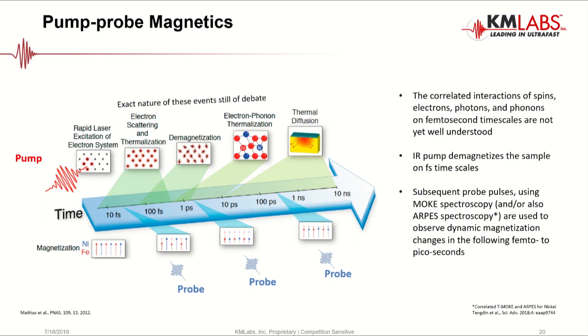One more example of the pump probe is to look at magnetics or spin behavior in materials. And it turns out for magnetic materials like iron or nickel or cobalt, when you hit them with a pump laser of the right wavelength and energy, an interesting series of events can unfold on the femto to pico and nanosecond time scale that include electron thermalization, a demagnetization step, and then eventually the diffusion of that heat into the surrounding lattice as the system relaxes. And what's interesting about this is that the exact nature and timescales involved in this process are still somewhat of a matter of debate and really not very well understood.